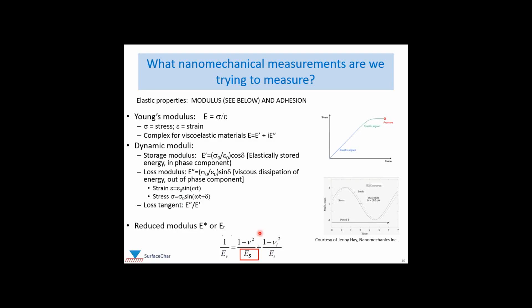So before I dive into research, I wanted to make sure we're on the same wavelength in two very important areas. The first one, what nanomechanical measurements are we actually trying to make? What are we trying to measure? So in AFM, we're essentially working in the elastic regime, and the most common mechanical properties that we're trying to measure are modulus and adhesion. Now modulus, we need to be a little more careful because there are actually different moduli that you can measure. It's a complicated parameter. At its simplest form, in static mode, there's Young's modulus, which is simply the slope, the constant, the relationship between stress, which is pressure, and strain, which is displacement in response to that. So in the elastic regime, this slope here would be our Young's modulus.